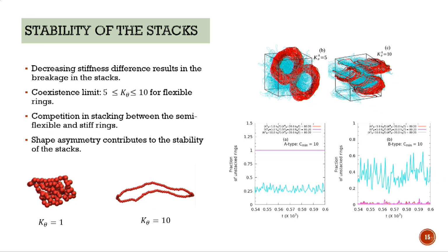And what we find is that up to 5, this structure remains stable, but the moment we went to 10, the stacks break down, because the flexible rings are not so flexible anymore, so they compete with the stiff rings.